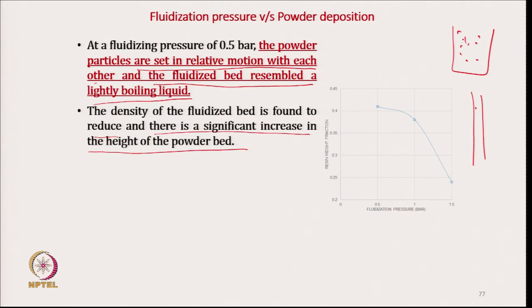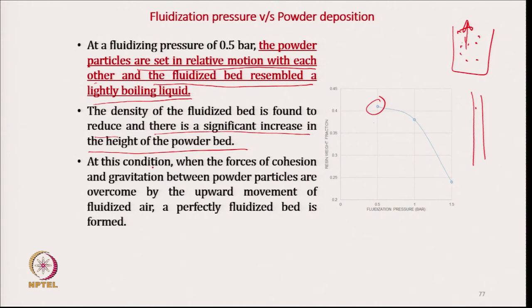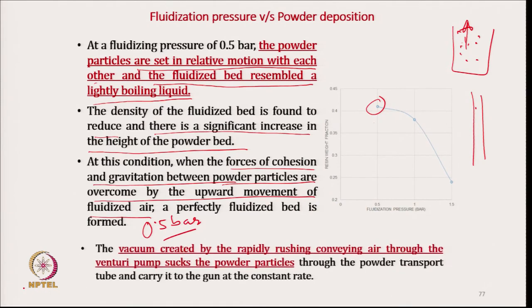That powder bed height increase will affect the deposition. At this condition, the forces of cohesion and gravitation between the powder particles are overcome by the upward movement of the fluidizing air. So, at 0.5 bar pressure, these things happen. The vacuum created by the flowing air helps in sucking the powder particles.